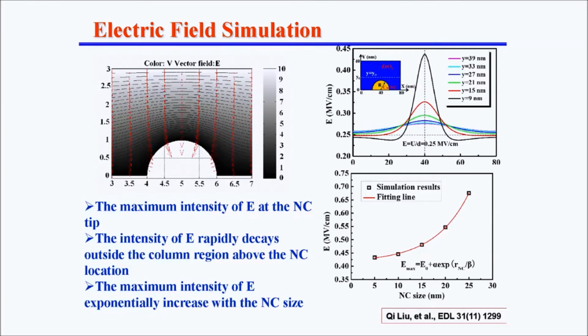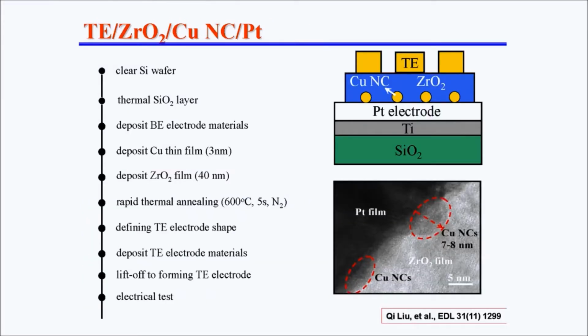Also, we simulate different nanocrystal designs and their relationship with the electric field. Based on these simulation results, we like to design an experimental device. This device is very simple. This idea is important, but the fabricated device is simple. We only deposit a very thin, 3 nanometer copper layer on the bottom electrode. Then after annealing, this 3 nanometer copper layer becomes separate nanocrystals. You can clearly see these copper nanocrystals.